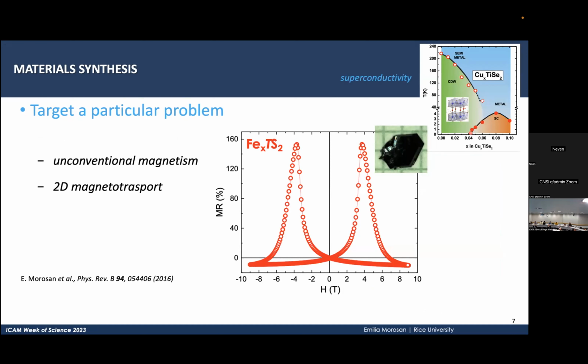It was just to see, actually. The motivation was that it was known that for some compositions, iron tantalum disulfide was antiferromagnetic, and for some other compositions was ferromagnetic. And what I really wanted to look for is a quantum critical point. That story didn't pan out, but great results came from looking at iron intercalated tantalum disulfide. And I have worked on this and related systems for maybe 7 or 8 years since.